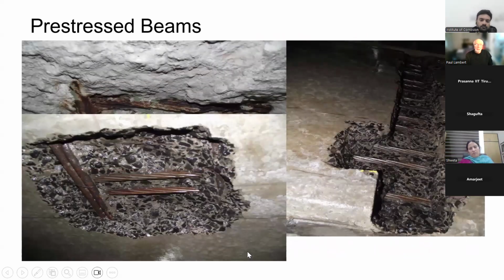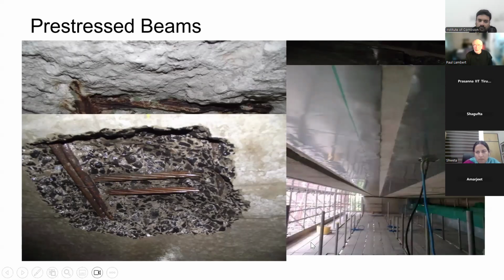Other areas where that type of system has been found to be useful is on treating pre-stressed beams. Now, anybody who's done the theory on CP will know, they go, oh, you can't use cathodic protection on pre-stressing because you get hydrogen embrittlement. Well, it's true that some steels will be susceptible, not all steels, and usually the ones in these types of pre-stressed beam structures are not susceptible. That aside, overprotection is not a good thing. It can generate hydrogen. But if you use a galvanic system, it can't overprotect sufficiently to generate the hydrogen.